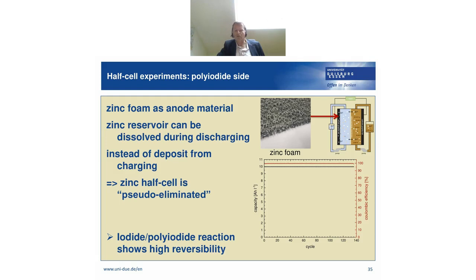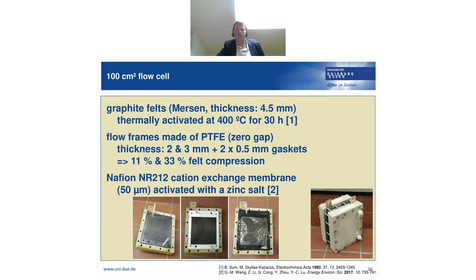And we have here around 140 cycles recorded for several times with a high reversibility. So we think that the polyiodide reaction is highly reversible. It can maybe be accelerated with the help of a catalyst, but this is quite stable. And we think that reversibility is not so good on the zinc side. So this is where we focus on at the moment.